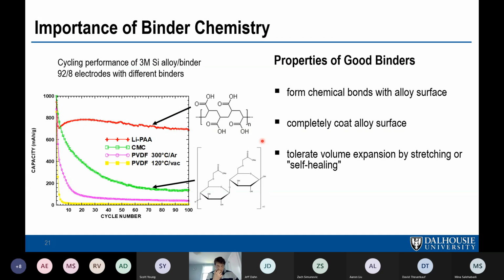You could get silicon to cycle a lot better, though, if you use a different binder than PVDF, a functionalized binder. So here's a plot of a 3M silicon alloy, which is basically a silicon iron alloy. And this is a conventional coating with PVDF. If you heat up PVDF, it gets a little better. This is a CMC binder, and this is polyacrylic acid. And essentially, the more carboxylic acid groups you have, the better cycling you get for these binders.